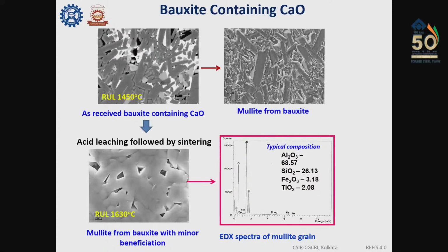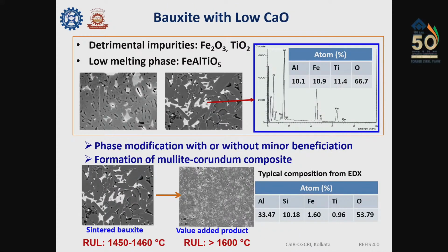In the second category, where CaO is low, the detrimental impurities are Fe2O3 and TiO2. The low melting phase is iron aluminum titanate, and that is seen from the EDX spectra of the low melting phases. We did the phase modification with or without minor beneficiation, and we promoted mullite-corundum composite formation by restricting the low melting phase formation, which we achieved by converting it to mullite. You can see in the microstructure that there is almost no liquid phase, and the RUL value is enhanced from 1450 degrees centigrade to 1600 degrees centigrade.